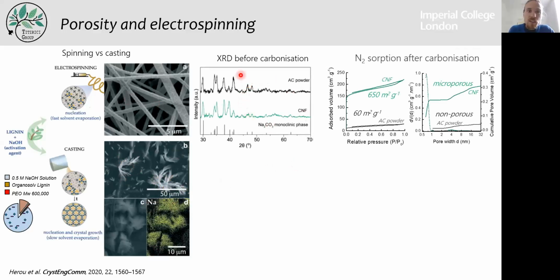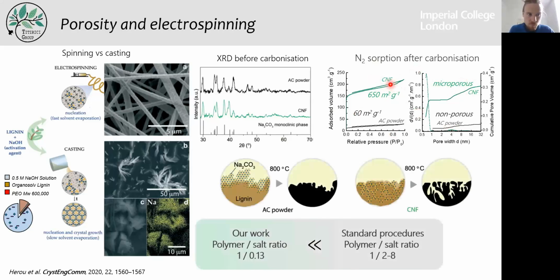those crystals using XRD on both the fibers and the casting powder that we call AC powder, and we can see that this is sodium carbonate. We probably also have sodium hydroxide, but since some of it is amorphous, we couldn't really assess its presence. After carbonization and washing, we measure the nitrogen sorption, and for the carbon fibers we obtain a really high microporous surface area of 650 square meters per gram, versus only 60 for the casted powder. I'm saying really high surface area not compared to the literature, but just compared to the amount of salt that we have inside the solution.